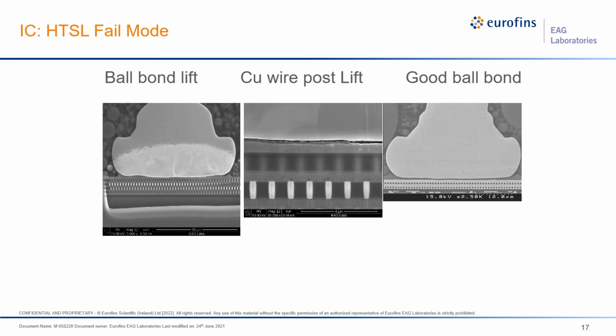This slide shows some examples of failure mechanisms that occur because of high temperature storage life. The intermetallic growth will cause separation between metallic layers, and this is common with the ball bond, where we see a lift in the image on the left, and there we see a copper wire post lift in the image in the middle, and on the right is a good ball bond.